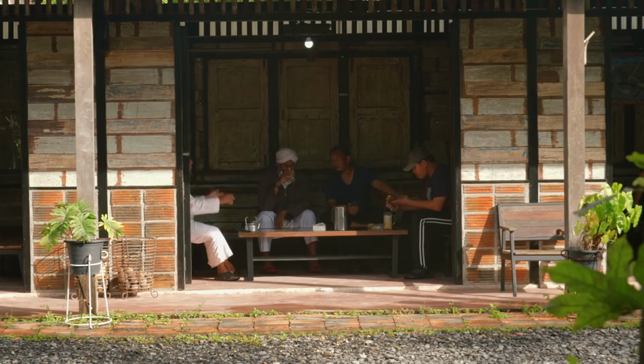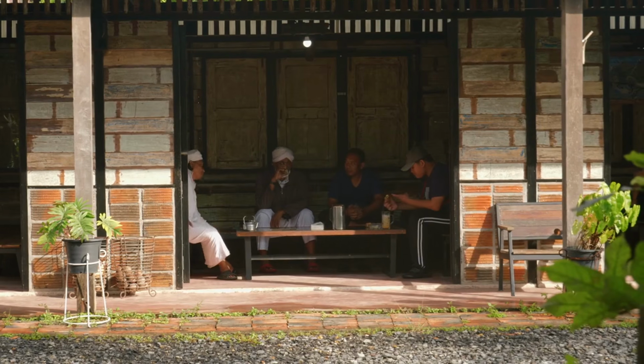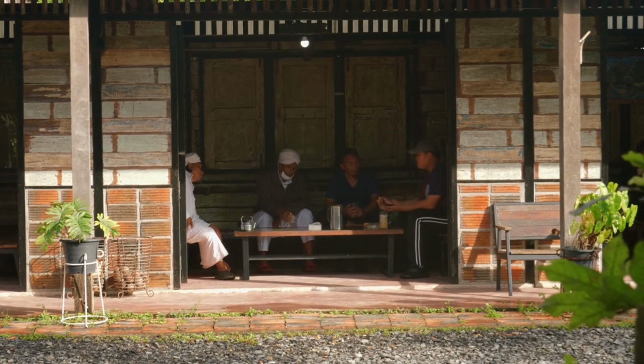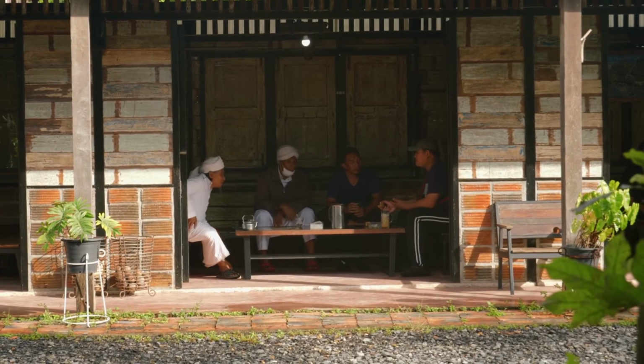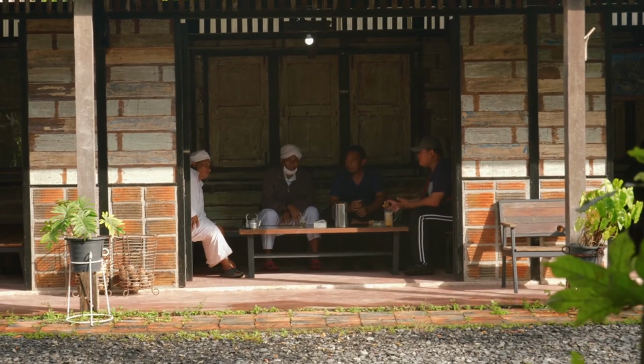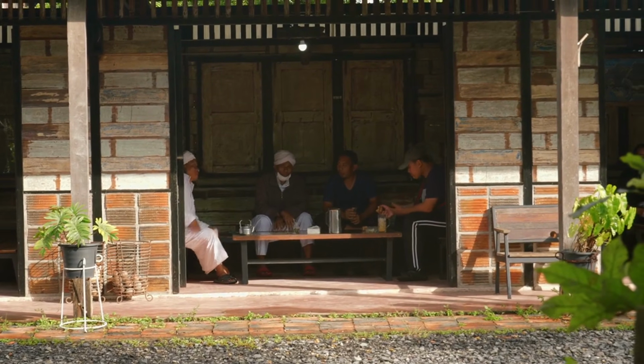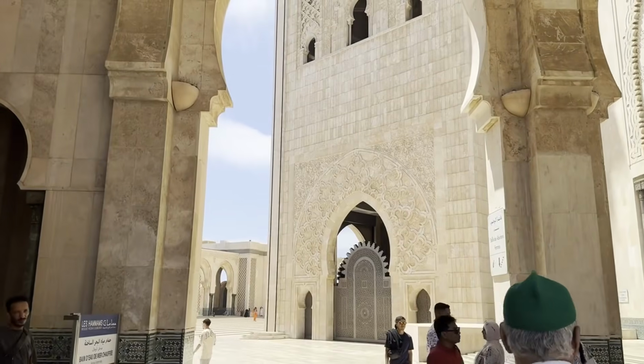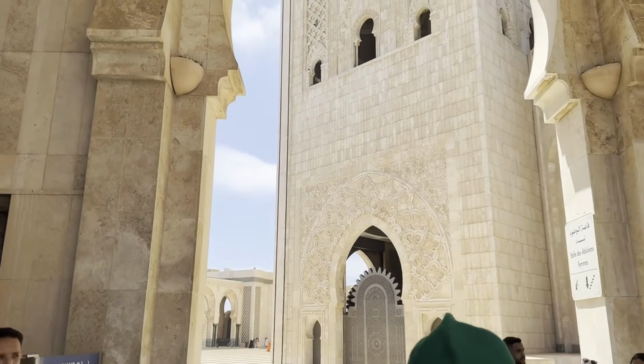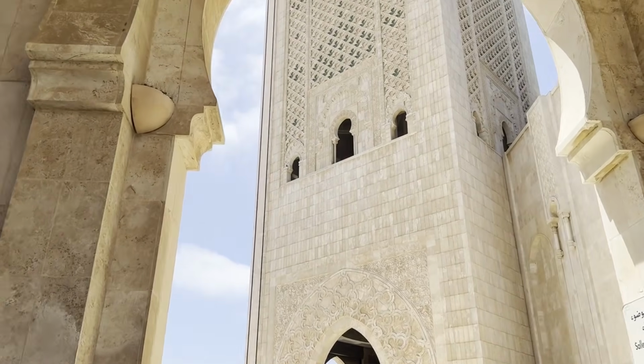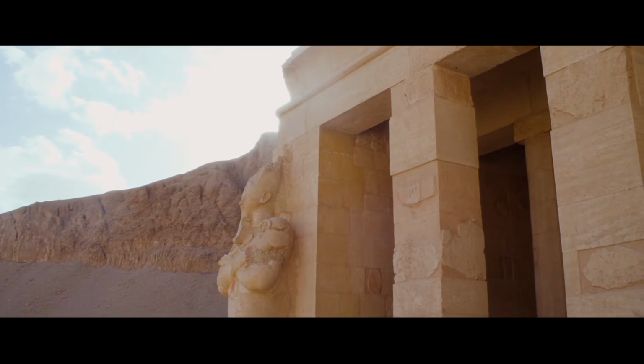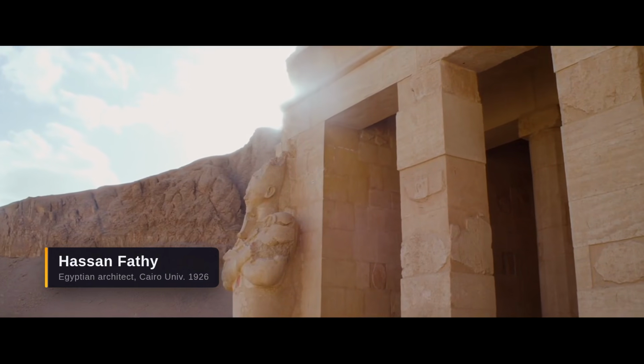The results from monitored units in Luxor Governorate showed interior temperature reductions of 19 to 22 degrees Fahrenheit, compared to standard brick and concrete construction. That's not a comfort improvement. That's a survival improvement. Hassan Fathy himself deserves more than a passing mention here, because his career embodies the intellectual lineage this technique sits within.